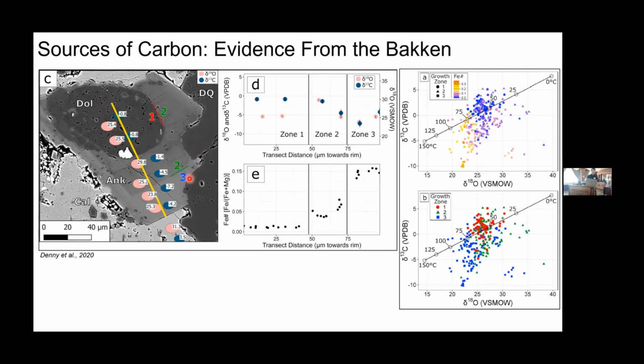And so what we're looking at along this transect are carbon and oxygen isotope measurements. This is using a technique called SIMS, where you can get about a 2 micron wide sample of a carbon or oxygen isotope, which is kind of cool.